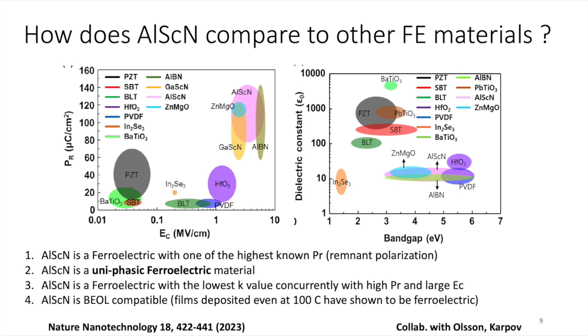For high temperature applications, you have to consider several things. Even if a material appears better than aluminum scandium nitride at room temperature, you have to consider the elemental stability of its elements at elevated temperature. For instance, somebody may say, oh, what about zinc magnesium oxide or gallium scandium nitride, right? It may appear better than aluminum scandium nitride at lower temperatures because the coercive field is lower. The issue is zinc and gallium will diffuse quite readily at elevated temperatures, making it a nightmare to maintain ferroelectricity or appropriate composition. So not only do you want superior composition, but various thermodynamic mechanisms start kicking in at elevated temperatures. My view is that scandium is a very high temperature stable metal. Aluminum itself is not a high temperature stable metal, but aluminum, when combined with nitrogen, is extremely high temperature stable, because aluminum nitride is one of the most well known refractory materials.